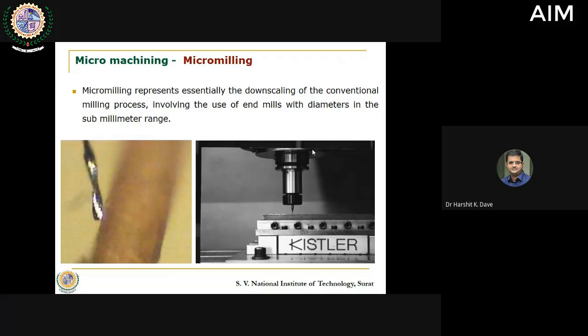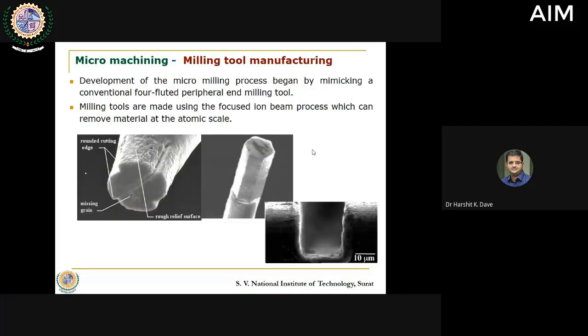Another task that we tried to carry out is related to micro milling. Micro milling represents the downscaling of the regular conventional milling process itself, wherein you use end mill cutters just as you use in the milling process. But here the diameter of these end mill cutters is in the sub millimeter range. They are too small, less than 1 mm diameter. There is an interesting work carried out by a group under Dr. Bamberg at University of Utah, where they have tried to produce a 4-fluted peripheral end milling cutter, something like this. This is what they tried to produce, an end mill cutter of this shape, a peripheral end mill cutter.